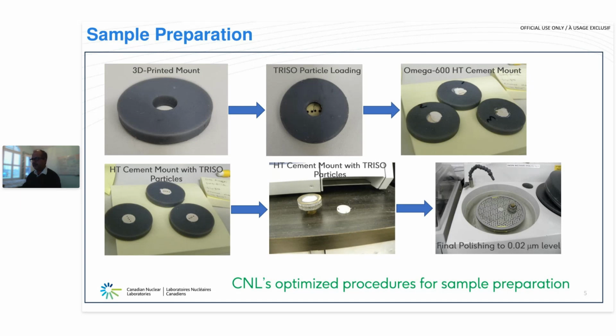The multiple of them, and then we take this cement puck out of the 3D printed mount and use our metallographic polishing routine to polish these pucks with the high temperature cement mounts with multiple TRISO particles to a final polishing level of 0.02 micron silica level on the diamond pads.